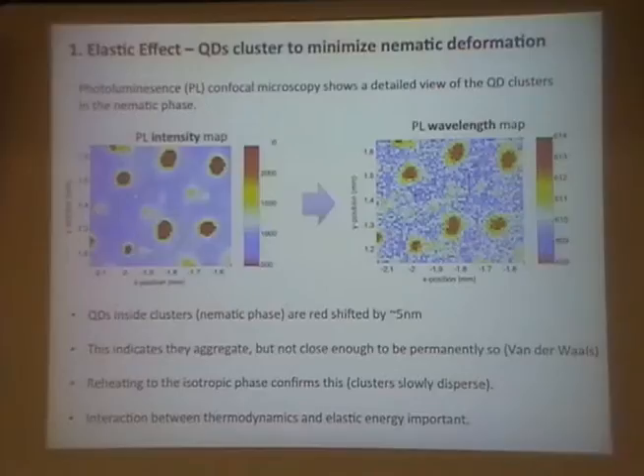So we talked about this elastic effect that I mentioned before, the propensity to cluster locally. You start off with particles everywhere in the isotropic phase, you cool into the nematic, and particles from nearby groups group together in a local cluster. Here we can see a photoluminescence intensity map of a small area. You can see some nice clusters. You can note here that actually quantum dots are everywhere. And this is a very low concentration, about 0.05 to 1 weight percent. We're certainly not loading them up super high. But they locally cluster. This is an intensity map, so we can see they're all here in these blobs.